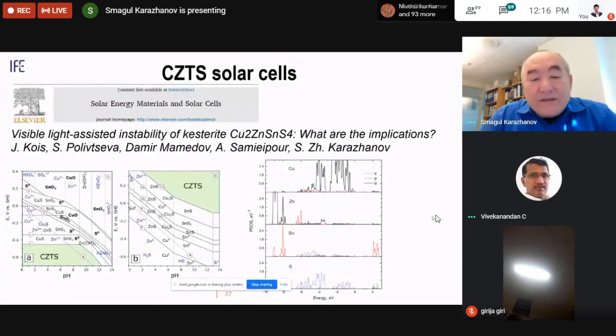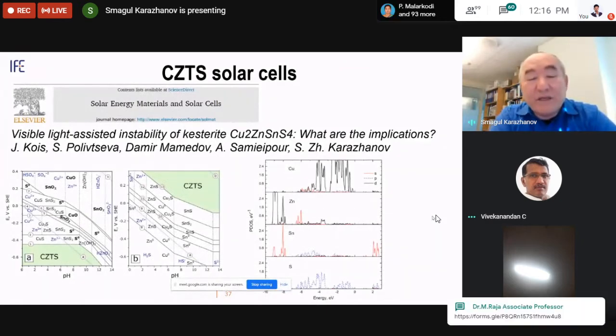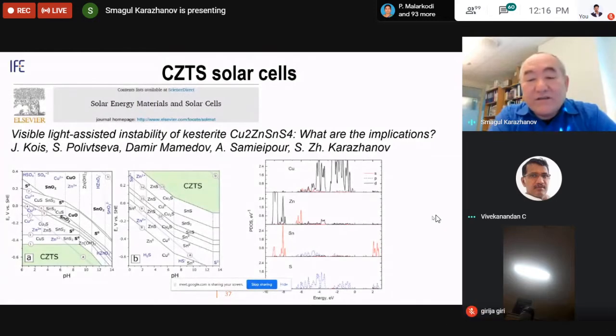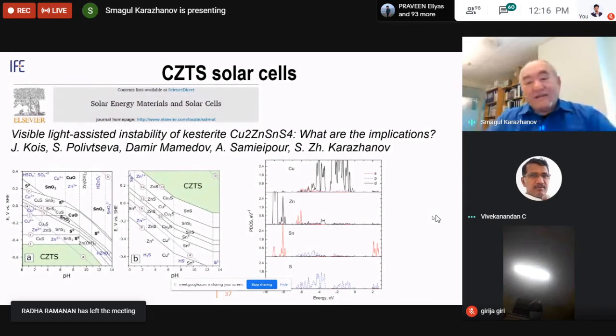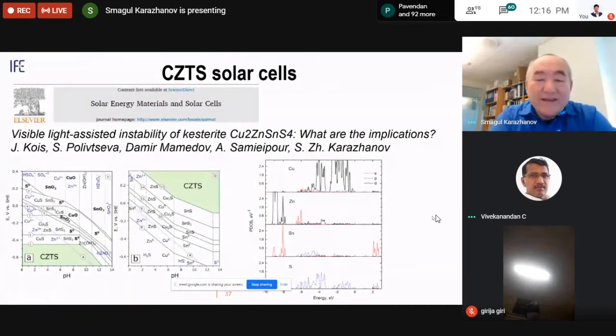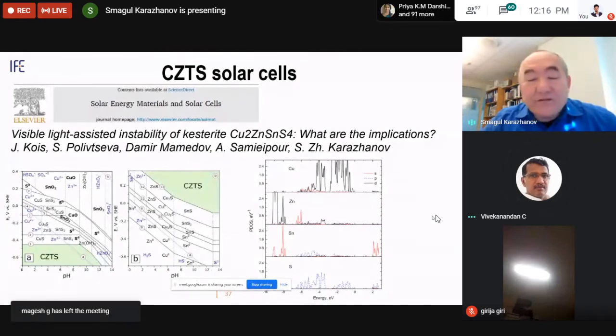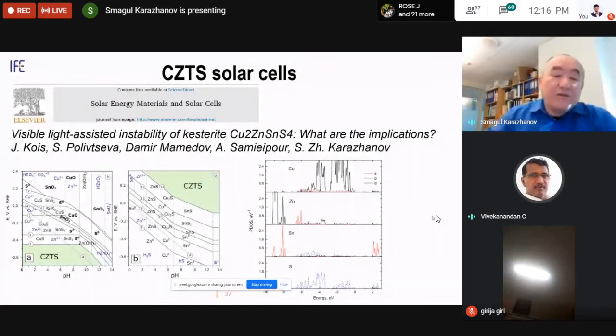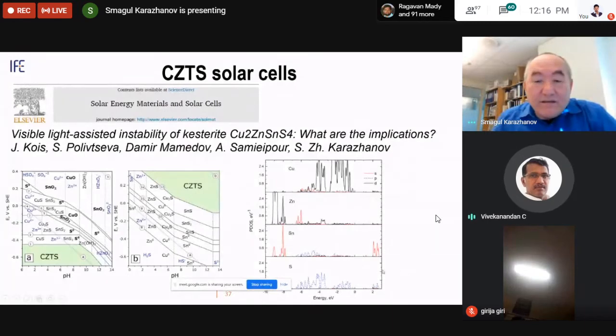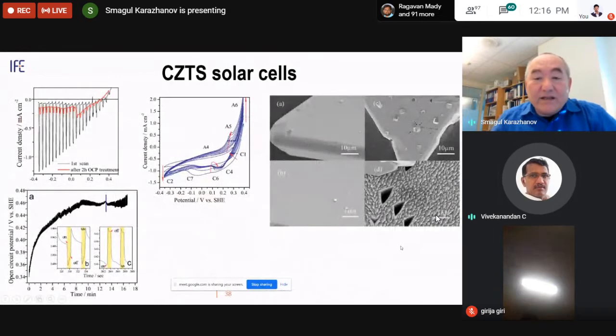And when, for example, the CZTS is illuminated with sunlight, an electron can be transferred from the valence band to the conduction band minimum. The conduction band minimum consists of tin states. And when the charge state of tin is changed from 4+ to 3+, then tin starts to rearrange the lattice around itself. And as a result, even if the CZTS is deposited by magnetron sputtering and in a very stoichiometric way, after some time it will become an unstable material.